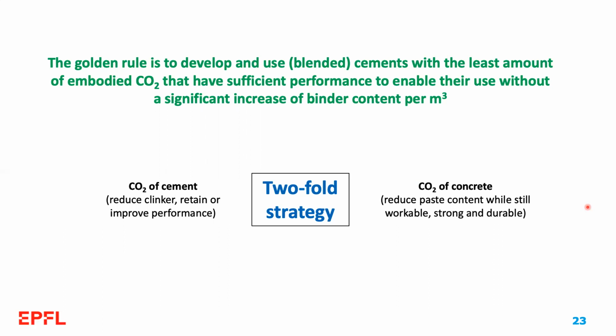We need to consider the two scales simultaneously because otherwise we will not achieve the optimum CO2 reduction per cubic meter of concrete. We need to consider simultaneously the CO2 of cement, which is proportional to, or the same as saying, we need to reduce the clinker and retain, or improve, the performance. And at the end of the day, we need to reduce the CO2 of concrete. So we need to reduce the paste content while remaining workable, strong, and durable. And this is very related to the development of more advanced admixtures that enable us to do this in a more efficient way in the future.